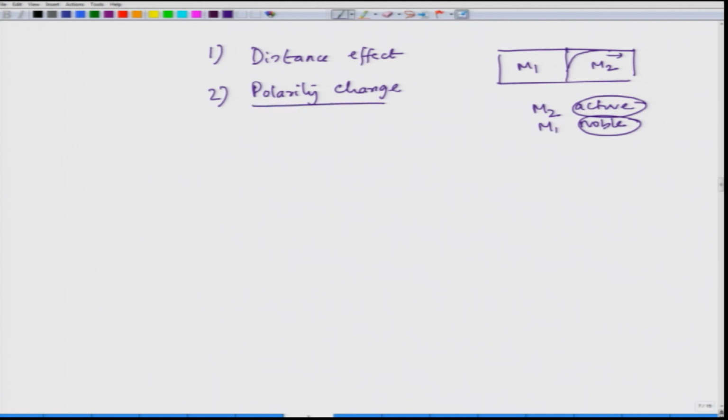Sometimes, though we design the couple for galvanic protection of a metal, if we do not look seriously at what happens with the change in condition, the metal part which is active and gives a sacrificial effect to protect the other metal part may change polarity, and the metal part which we want to protect would corrode more than expected.